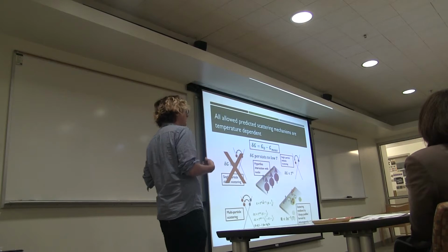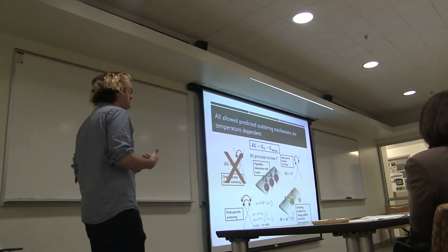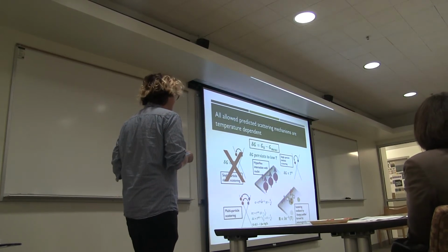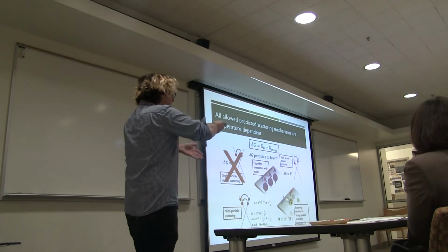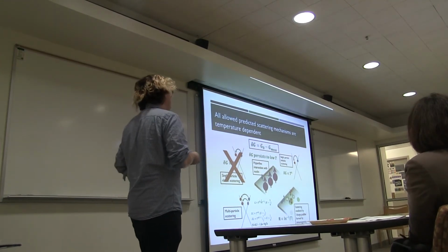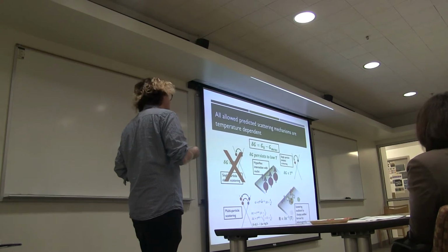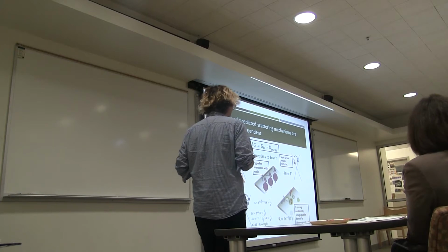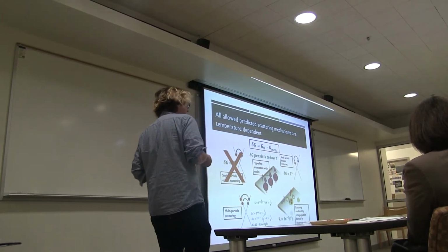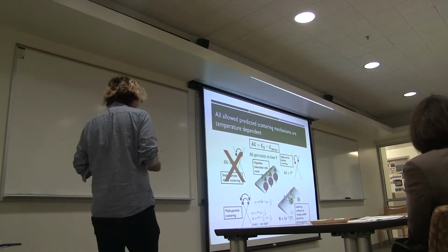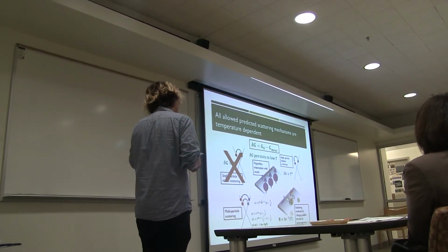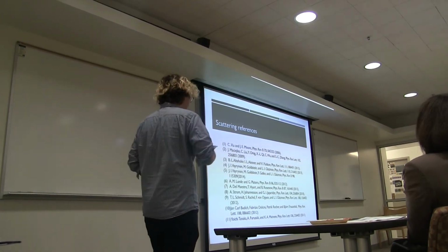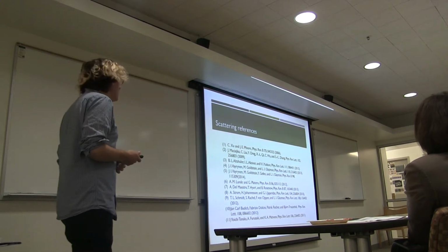and their temperature dependencies are all too strong to be consistent with our data. The closest to being consistent is this picture of inhomogeneity in the bulk, forming quantum dots which the edge states can tunnel into and out of. And in a certain temperature regime, based on the size of the quantum dots and various other parameters, you can get a pretty weak temperature dependence of the resistance. I would still say that this natural log squared, or 1 over natural log squared dependence is not really consistent with what we see. So here are references for the scattering. There's been a lot of theoretical work on it.